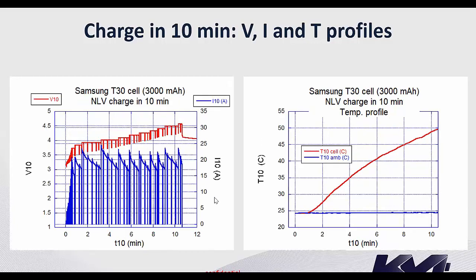And then we went to about 10 minutes, maybe 11 or 10.5 minutes or something. So you can see here the voltage profile, a succession of plateaus with the plateau steps here. And this is where the current goes to zero. We call it rest. And you can see on the right hand that the temperature during the charging in 10 minutes kept below 50 degrees and almost reached 50 degrees after 10 minutes of charging.